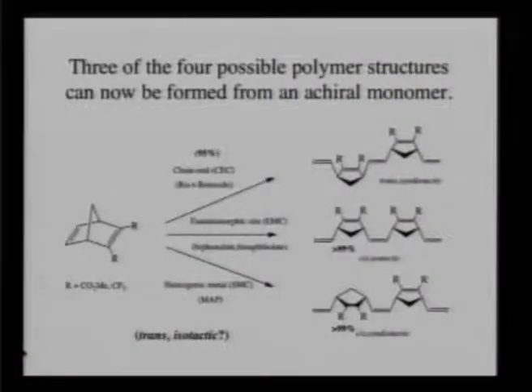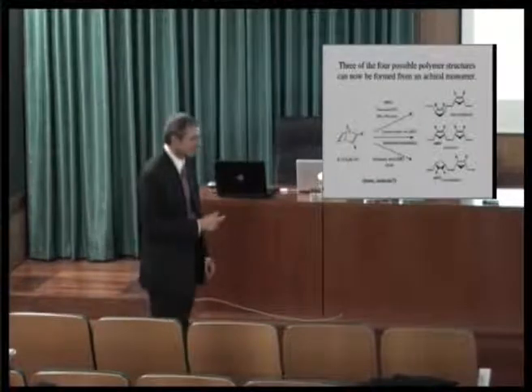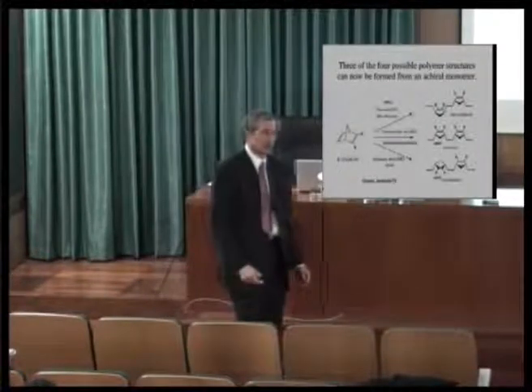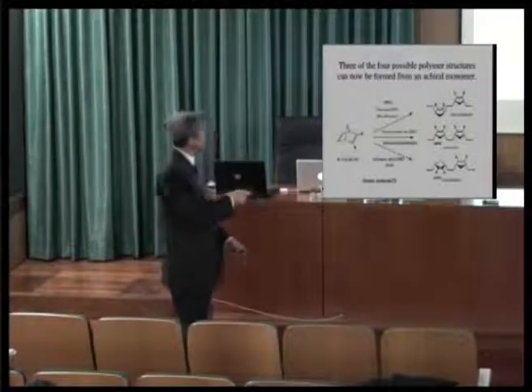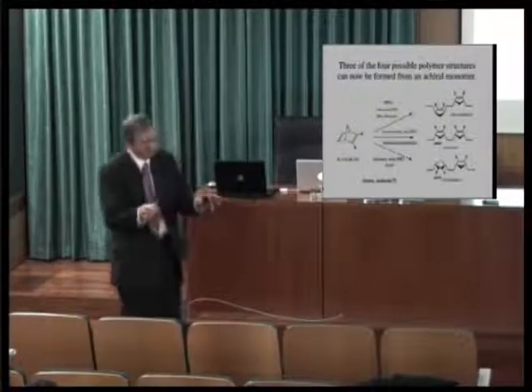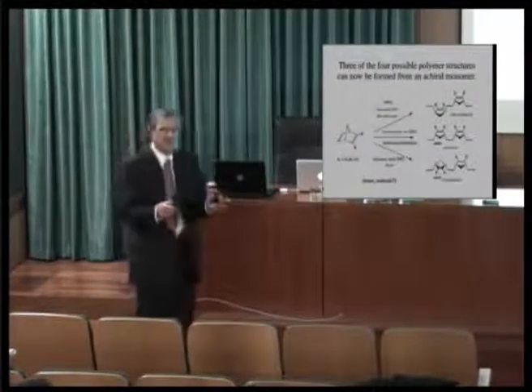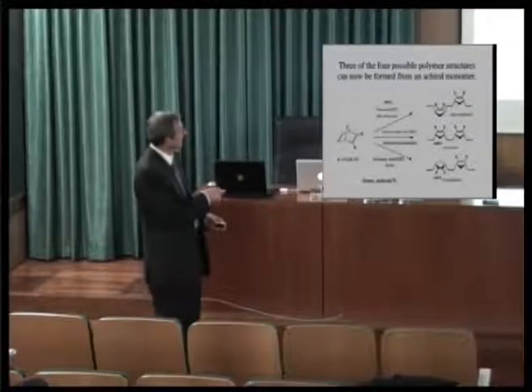Well, we can use then these MAP catalysts to make the syndiotactic polymers. We can make the isotactic polymers, and we can, through a chain end control method that I don't have time to go into, make a trans syndiotactic version. The only remaining one is trans isotactic, and we now think that we can make those also. So you can make different polymers, entirely different polymers from the same monomer, just by making different structures.